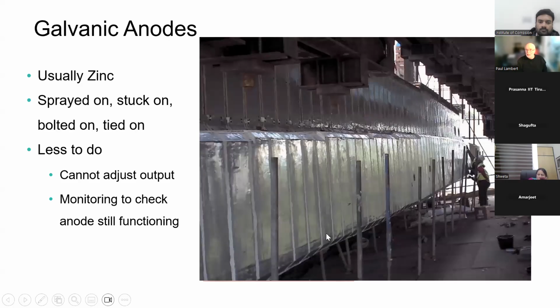And you can even get a sticky bag zinc. I say sticky bag, it's actually a hydrogel adhesive with an activator in it, something that will keep the zinc busy. You've got to make separate connections that link the zinc through to the steel. You can see these plates, a couple of plates that go through with a nail into the steel. This was on a joint where there was about a day to do something, and so there's very little time to do much. Went in, threw as much of this stuff on as possible, and it's actually worked surprisingly well.